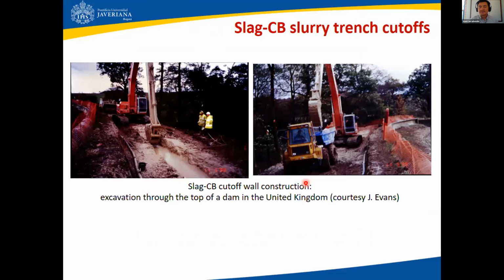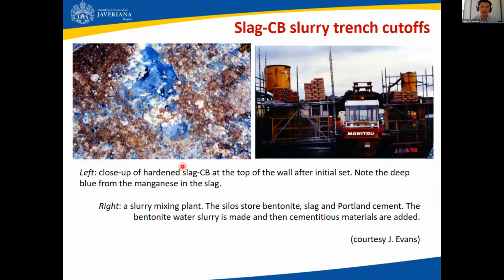As far as slag-cement-bentonite slurry trench construction for cutoffs, what you're looking at are some photos courtesy of Jeff Evans, and these photos are from the late 90s in the United Kingdom. This is an excavation through the top of a dam at that place, and that's where you see the process of digging the excavation and allowing the slurry to prevent collapse and to set in the initial stages of construction. And what you see here on the left-hand side is a close-up of the hardened slag-CB material at the top of the wall. And you can see a deep blue coloration due to the manganese in that slag.